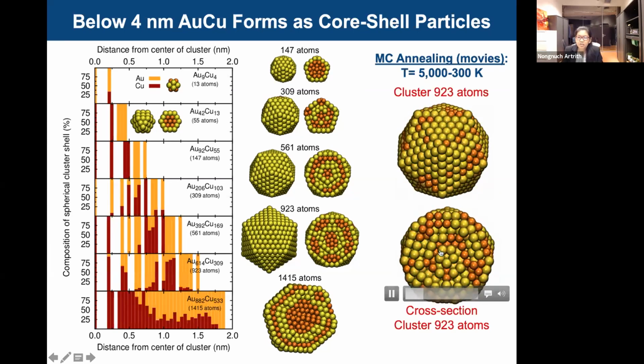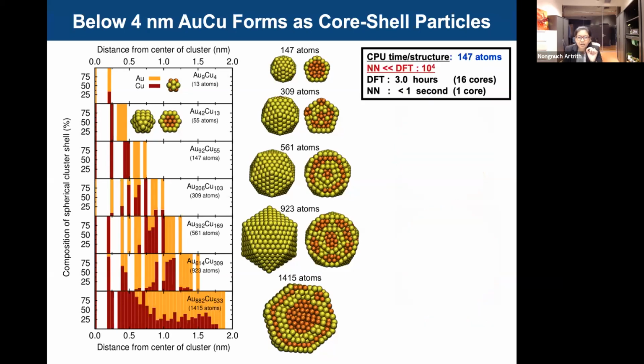We see that the gold, the yellow, and the copper atoms, orange here, rearranged in core shell ordering in small nanoparticles, in this case up to 4 nanometer cluster size, which is around 1,000 atoms. So in vacuum, gold prefers to be at the particle surface, like you can see here. And then take a look at DFT calculations: if we would do this simulation with 147 atoms, it would take around 3 hours on 16 cores.